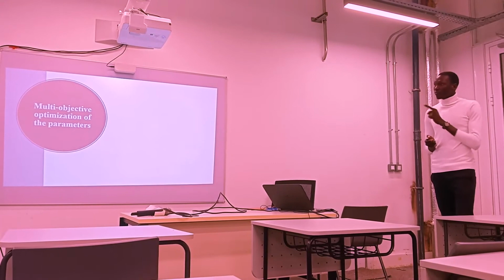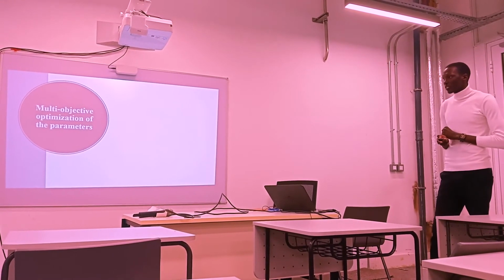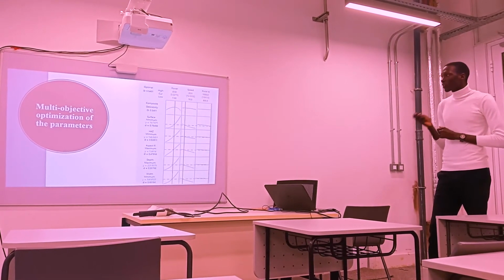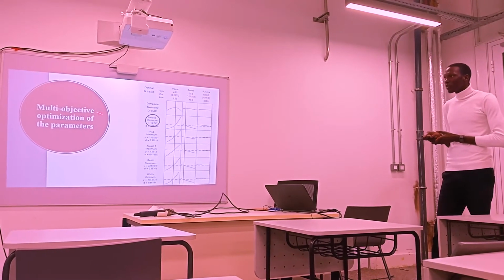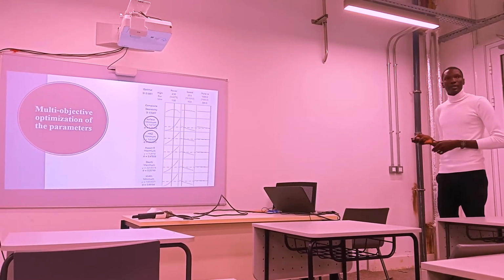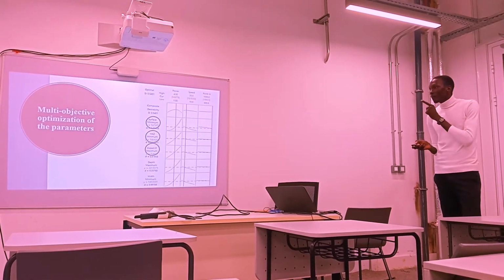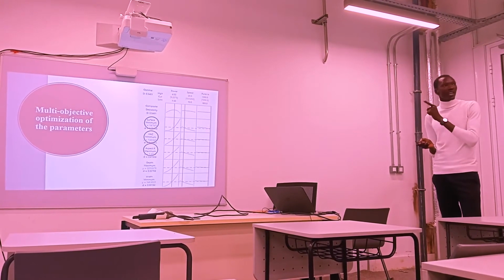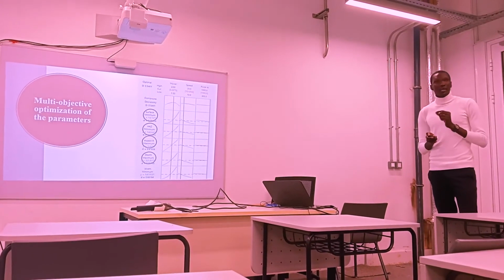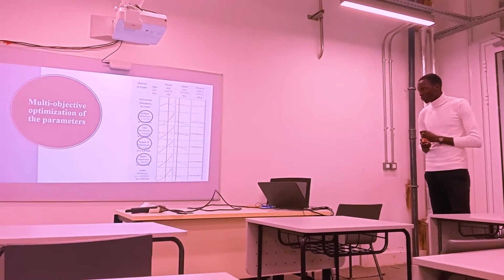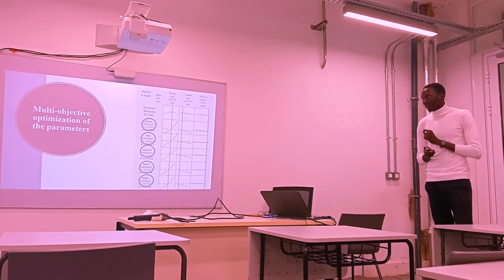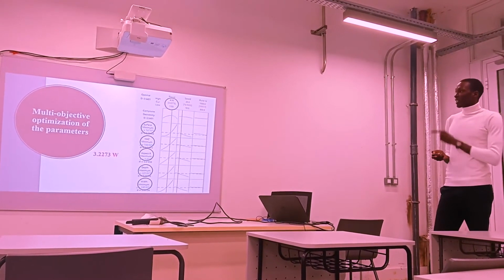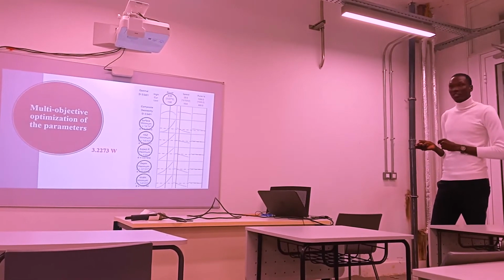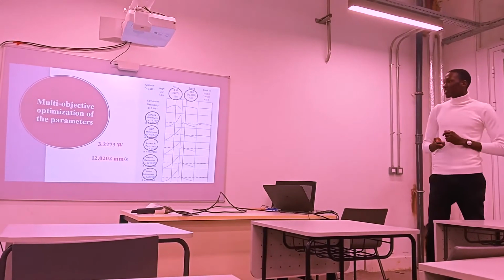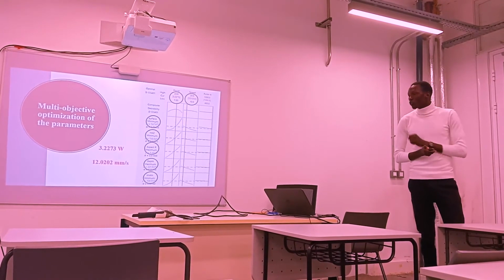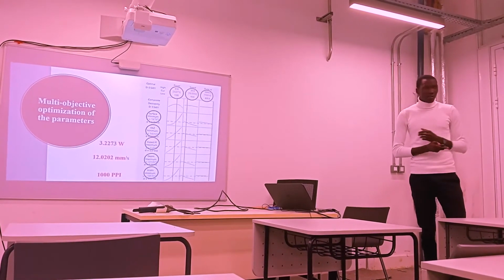Then, we did multi-objective optimization of the parameters. We got these results. The goal was to minimize surface roughness, minimize heat affected zone, maximize aspect ratio, because we need high aspect ratio, and maximize depth to get maximum aspect ratio, and then minimize width. Now, these are the optimal values we got. For power, it was 3.2273 watts, and for speed, 12.0202 millimeters per second. And the pulse rate was 1000.